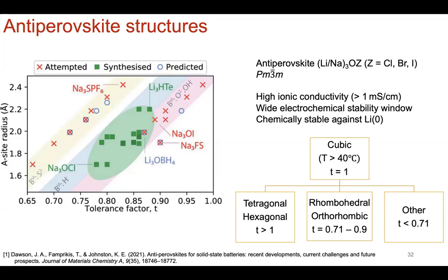And on top of that, the perovskite literature would already inform us, huge body of literature on perovskite structures, not specifically for lithium ion conduction, but just perovskite structures in general, tells us that the local structure of these compounds are highly sensitive to any sort of distortions as well. And that comes from all the studies on ferroelectricity, pyroelectricity. So we can draw from a lot of the studies that have already been done to tell us, even if we synthesize a compound and understand its bulk structure, how it performs at the local scale and how it performs as an ion conductor really depends on our understanding of that local structure right at that temperature. So it's not always so clear cut in how we tie the structure to the property and then to the electrochemical performance. Okay. So those are some of the caveats to think about going into trying to engineer and design these antiperovskite structures for fast ion conduction.